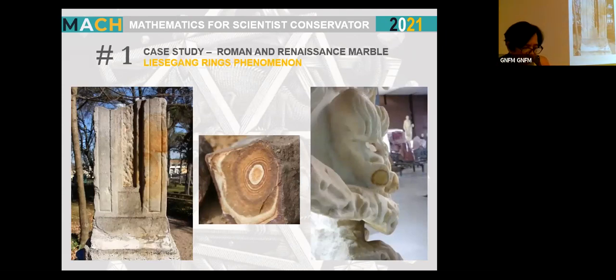The first case study regards the Roman and Renaissance marble and the Liesegang phenomenon. In this case, the conservative problem is represented by the iron stain that we often encounter on carbonatic stone. In fact, among the numerous conservative issues regarding stone artifacts, the presence of stains caused by metallic compounds, in particular iron ones, turns out to be one of the deeply felt problems, both from the aesthetic aspect and the chemical-physical